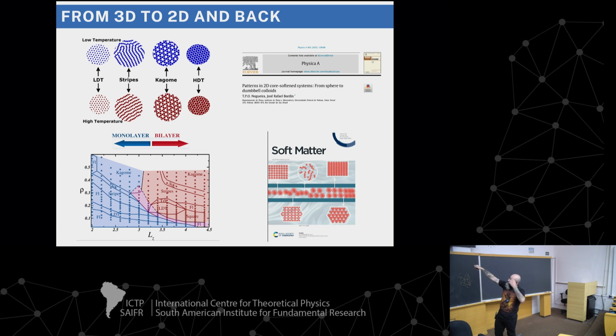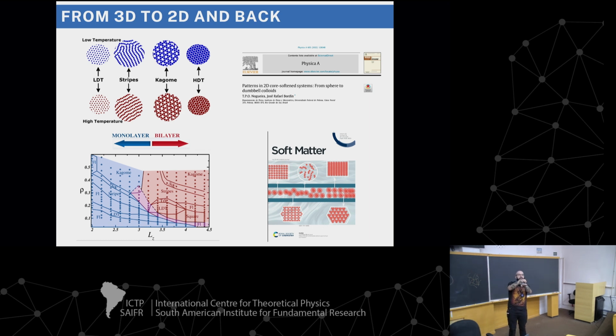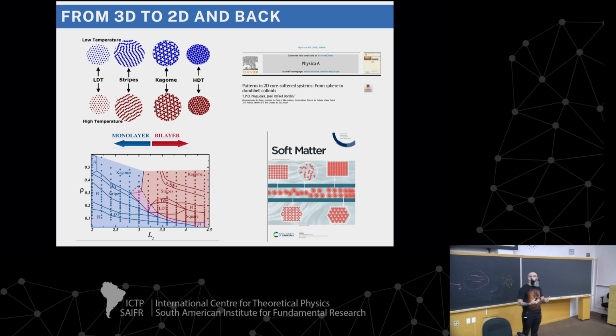And a really nice finding that we published this year is that if you allow the system to have not only one layer but two layers, you can create new phases that you did not observe in the pure 2D system. Here, we create a square-like phase. So we can control the shape, how these particles aggregate, or the morphology, basically by controlling the dimensionality of our system.